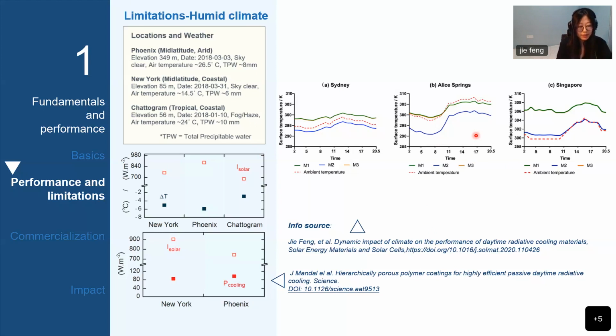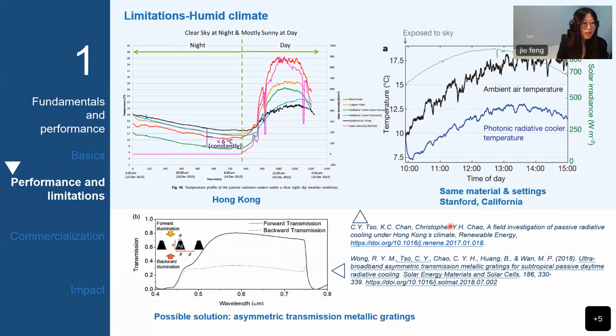We found that the 3 materials can almost all reach subambient in the desert city, which is Alice Springs. Right here, they can all reach subambient temperature, but all have above ambient temperature in Singapore, whilst in Sydney, they have intermediate performance. Another example is that for the same material using identical experimental settings, the cooler reached up to 5 degrees subambient in California, you can see on the right side, but cannot be cooler than air in all testing conditions in Hong Kong, which is here.